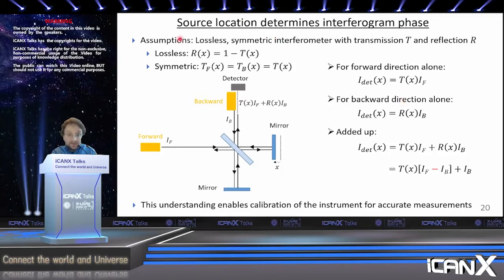So if you make some very simple assumptions that are very reasonable about most Fourier transform spectrometers, you notice that if you have forward emitting sources and backward emitting sources in your setup, what your detector is measuring is always going to be somehow the difference between the intensities of your forward source and your backward source. And so when the power of your forward source and the power of your backward source are about the same, which happens when the sample is close to room temperature, because this backward emitting background is a source at room temperature necessarily, then you have this minimum in your thermal emission measurements.